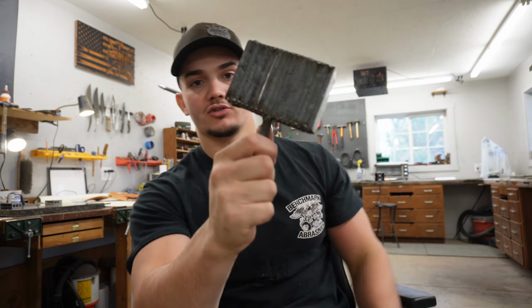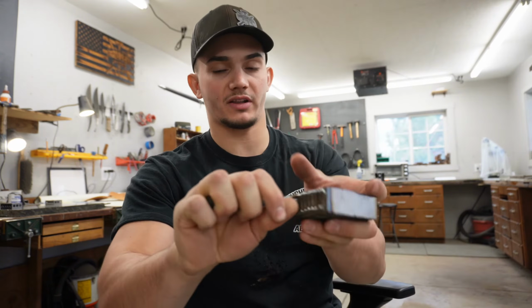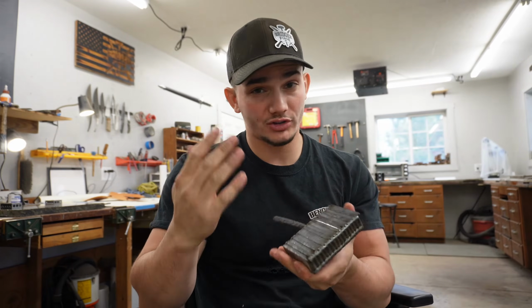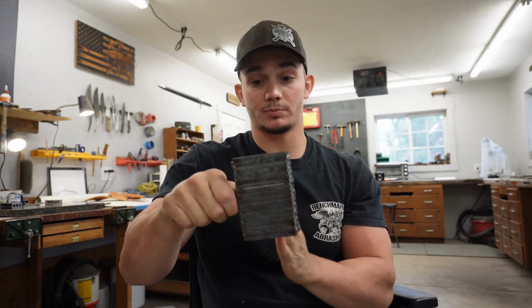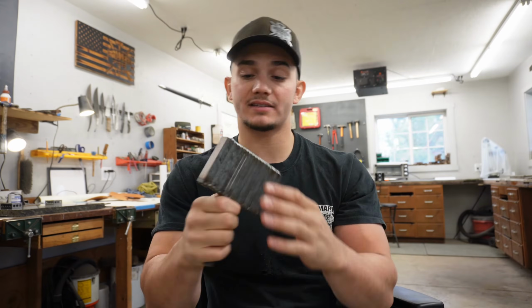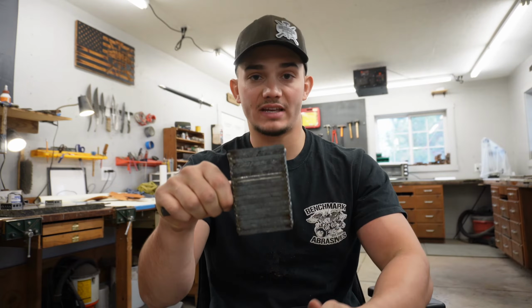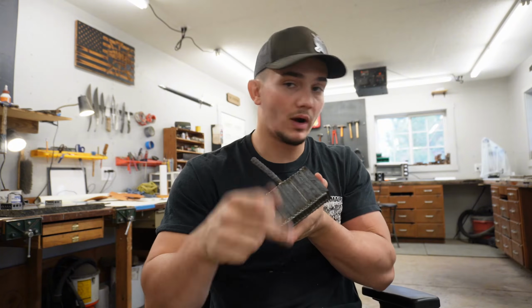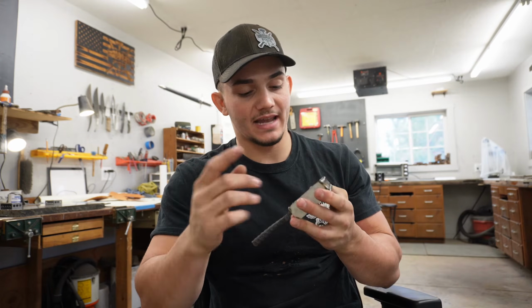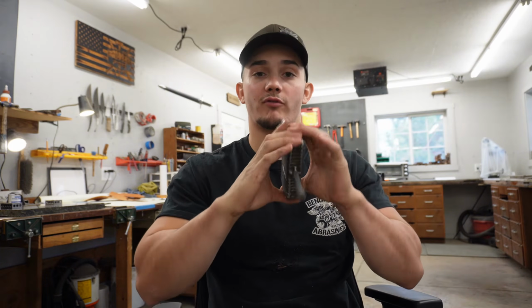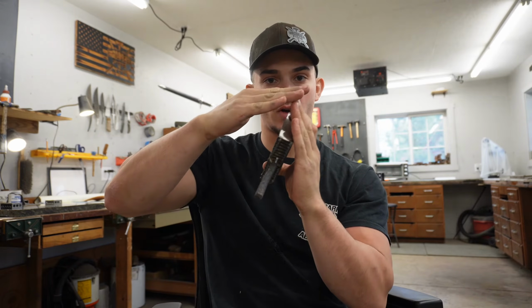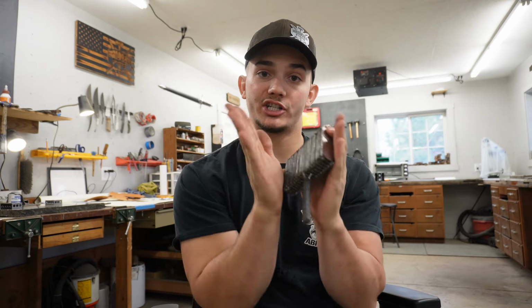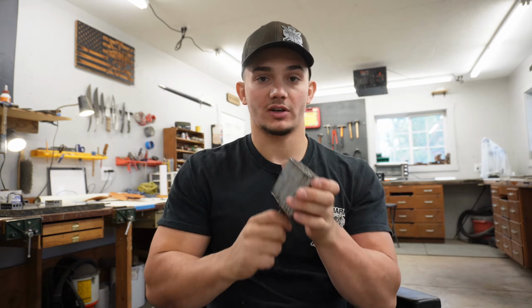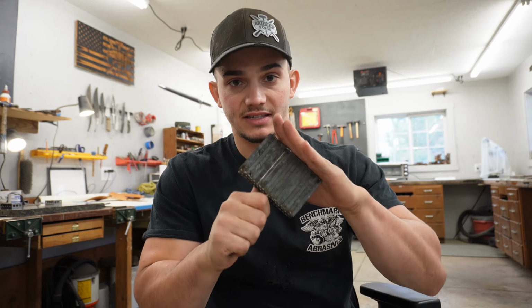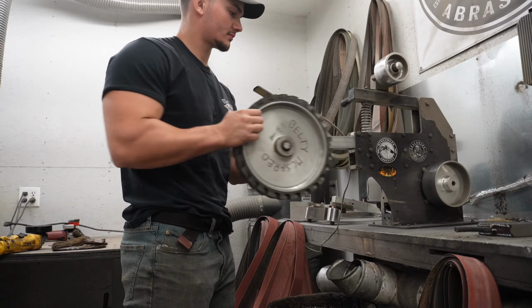and not rip apart. The second thing that we're just about to do is grind the faces so they're perfectly flush and flat. This is because there's also pressure being applied outwards during the splitting process. So when you're doing your splitting, sometimes what you'll get is delams on the faces as well. So what I'm gonna do is not weld every single seam on the face. Instead, I'm going to grind it flush so that when I forge weld it, there's no differences or overhangs in the layers that might trigger a shear when you go to split it down the middle. So I'm gonna get over to the grinder and grind these faces flush while I heat up the forge.